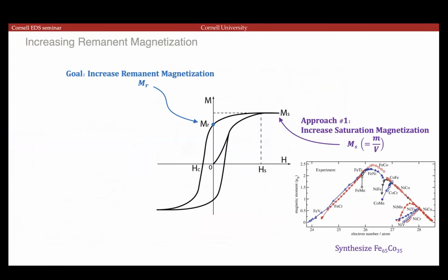You can either just completely shift the curve upward, like stretch it larger by increasing the saturation magnetization. And theoretically, this curve is well known in the field of magnetism as the Slater-Pauling curve. It compares the room temperature magnetic compositions that you can get from iron, cobalt, and nickel, which are the three magnetic elements at room temperature. And the highest magnetization is for iron cobalt, iron 65, cobalt 35. So we can do that.